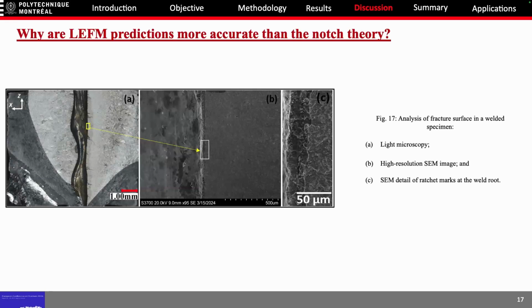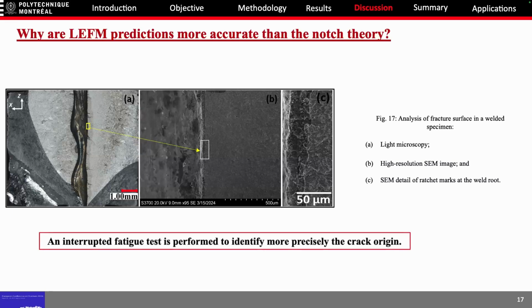So we did some fractography here to see what's going on. As you can see in picture B, for example, this is a detail of the weld root, and you can see that there is a step-like feature, and the height is different from the fracture surface. We needed to do an interrupted test to identify more precisely the crack origin of this step-like feature, which emanates many ratchet marks.